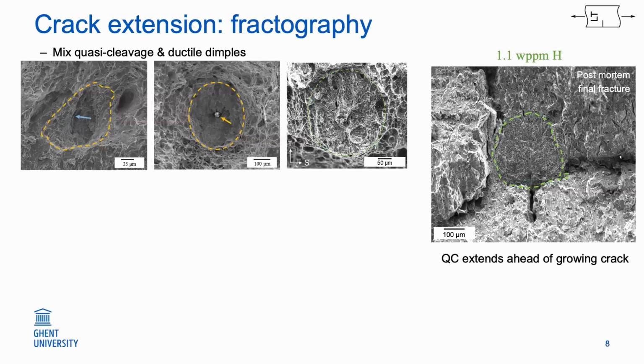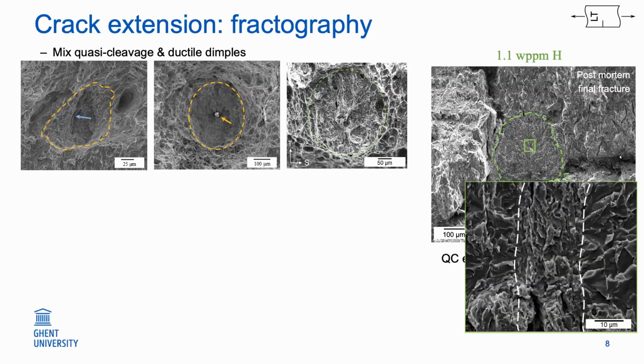They're often linked to some inclusions or maybe the bands, because as you can see in the highest hydrogen specimen, we did have some quasi-cleavage actually extending ahead of the main crack front. And then we could identify there this bainitic band, which is likely where the quasi-cleavage grew.